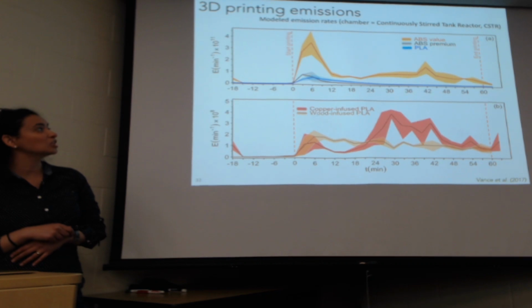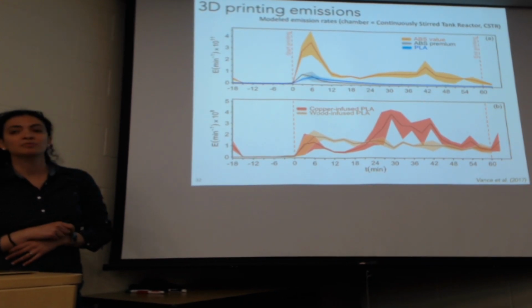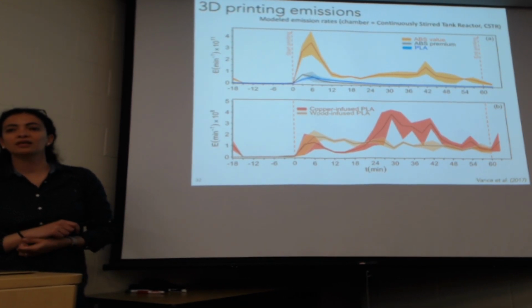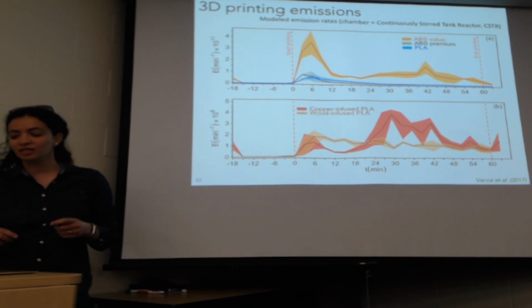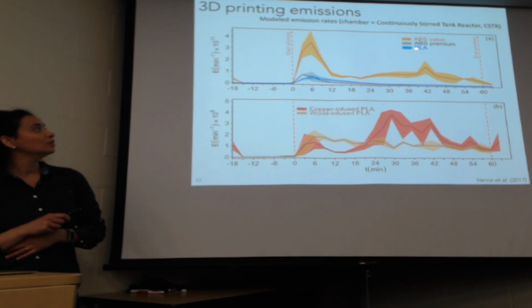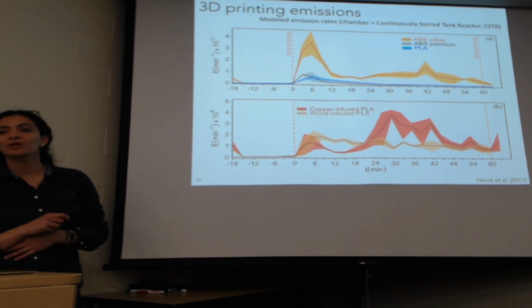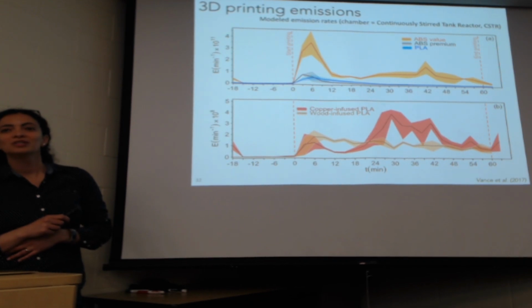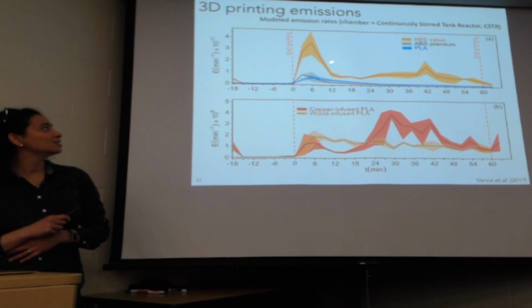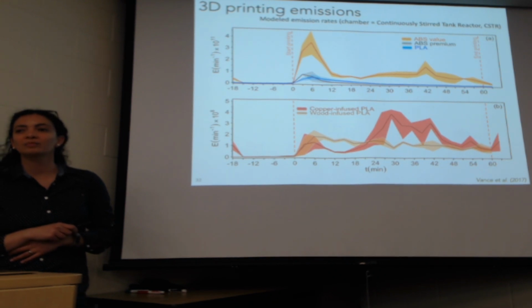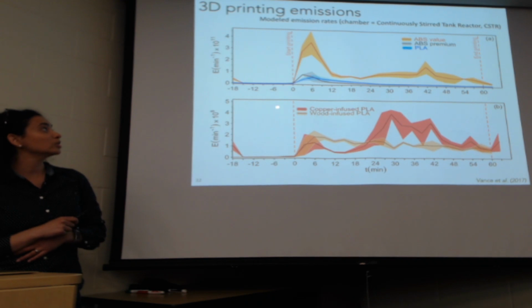The other interesting thing you may notice is that we tested 2 different types of ABS, and they had drastically different emissions. And the interesting thing is that ABS value emitted much more than ABS premium, and ABS value, as you can imagine, is the cheaper. So cheaper is, in this case, far worse. I don't know about the quality, the mechanical properties of the part itself, but in terms of emissions, it was much, much worse. We also noticed that there was a lot of emissions in the beginning for all these 3 cases, and not so much towards the end of the print job.